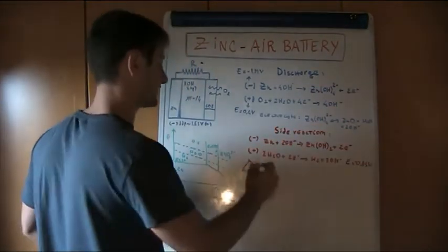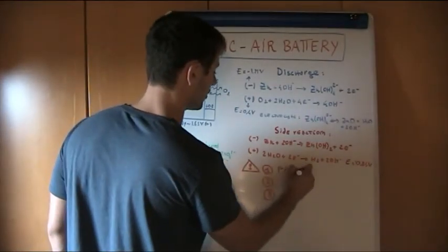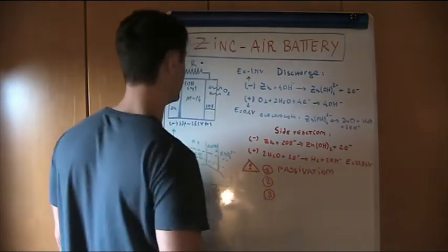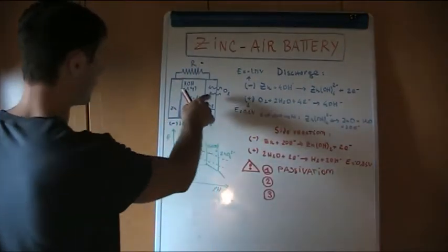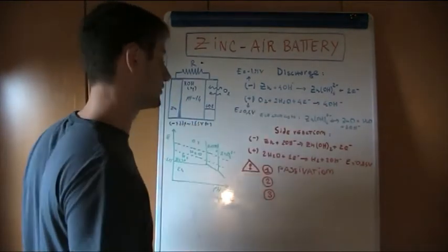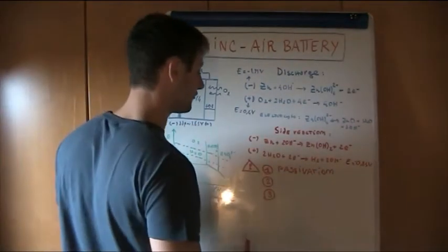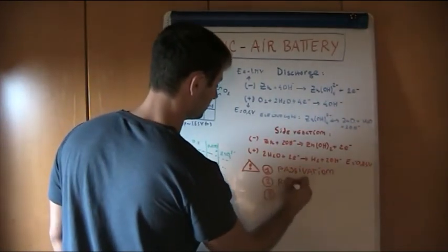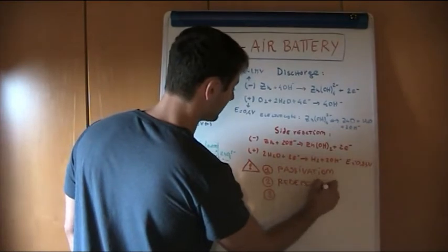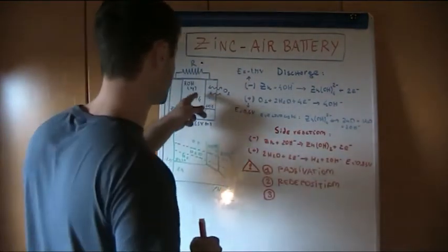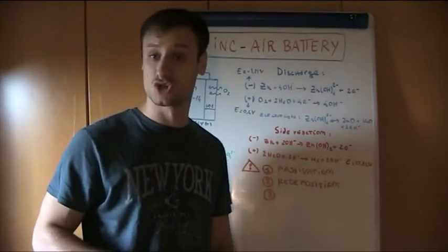And so, for instance, the passivation, the creation of an insoluble oxide film, hindering the diffusion of OH- as a product of these reactions toward the anode. We have focused our attention on the problem of bad redeposition, with even the possibility to close the circuit, breaking down the separation membrane and causing a short circuit.